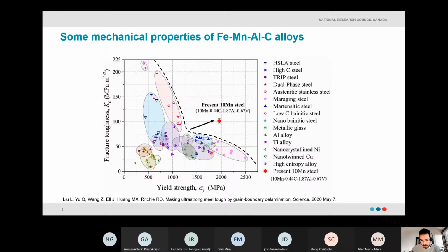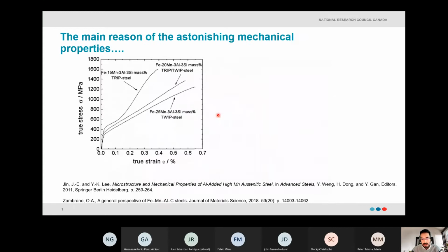So if we make the same analysis for other materials, we can see how the manganese steel stands when compared with them. With this material, it's possible to get a really high fracture toughness while keeping the yield strength. And what is the main reason for these astonishing mechanical properties? Basically, when we see the true stress versus strain curve for different manganese aluminum alloys, we can see that up to the yield strength, they behave similarly. But after, when the plastic deformation starts, there are different mechanisms that allow these materials to gain strain and gain stress. This is a strain hardening behavior, really quite interesting.